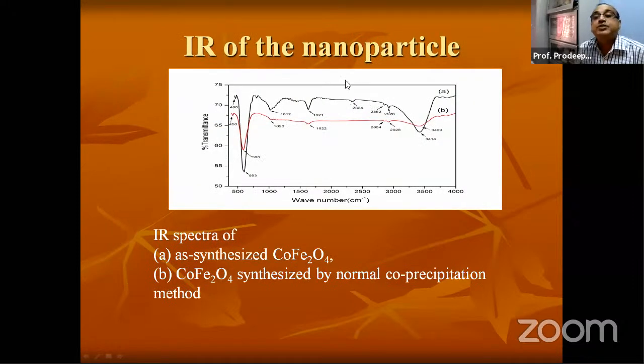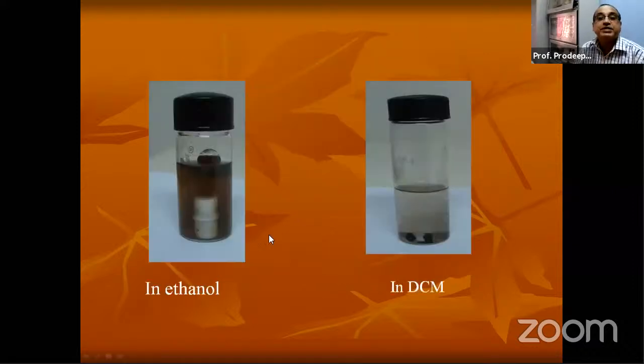And we have also studied the IR of the nanoparticle. You can see here, this is B, this is A. B is the one synthesized by normal co-precipitation. You can see here, this is almost flattened. And here, this peak shows the surface has a lot of hydroxyl functionality. So that is why it is more polar, and it is dispersible in aqueous or alcoholic medium. But since it is very highly polar, it is not dispersible in DCM or toluene or other solvents. You can see it is very interesting.